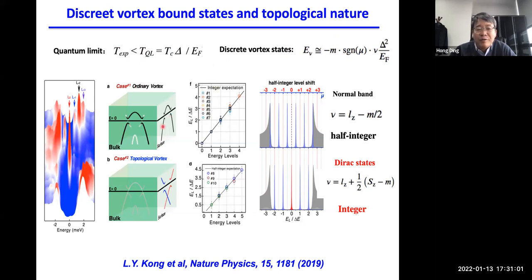Say in the ordinary vortex, if we have a Schrodinger state, this will become a half integer. So you have plus minus half, plus minus three halves, and so on. But if you have this Dirac state, this brings a pi phase, this Berry phase, and this will tend to become an integer because you will have an even number here divided by two.